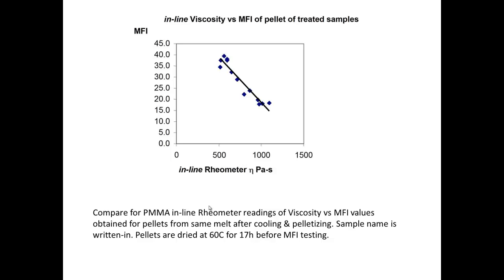Here we can destabilize the entanglement. That's, at least, the assumption that we advance: that we have touched what actually are the entanglements of a melt, and we have destabilized the entanglement to the point that the melt stability is different, and it takes a very long time, or it can be a short time. It depends on the amount of so-called disentanglement we have done, and the sustained orientation and the time it takes for sustained orientation to recover, in other words, to disappear, is also a function of the structure of the entanglement state, and a function of the